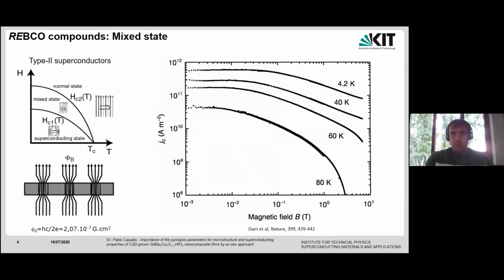So the first part, some basic knowledge about nanocomposites. Why do we need nanocomposites? As you know, REBCO and all the high-Tc superconductors have this mixed state in their phase diagram, and the presence of this mixed state is associated with the presence of these vortices, which are these flux tubes that can move depending on the magnetic field when they are in this mixed state, and this causes the current that flows in the superconductor to decrease quite a lot with temperature and also with magnetic field.